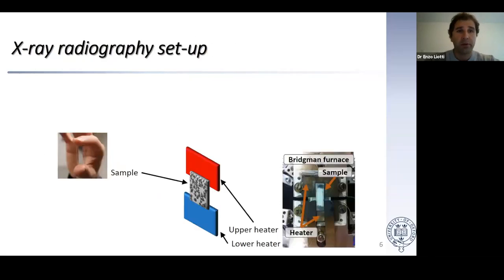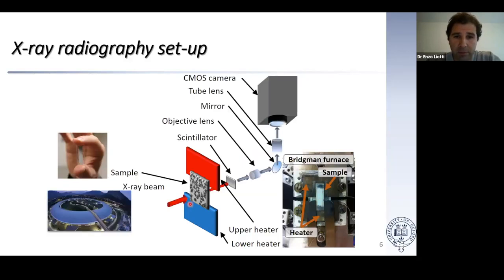A typical imaging experiment in X-ray radiography is not much different than when you go to the hospital and you get a radiograph. In the setup designed for solidification, we normally use what is called a Bridgman furnace, which has two small plate heaters, like you can see here, aligned vertically with a gap in the middle. The sample is positioned touching the two surfaces, and it can move up and down in certain conditions. The X-ray passes through the gap, and the X-ray transmitted through the sample is collected by an optical system that transforms the X-ray into visible light.